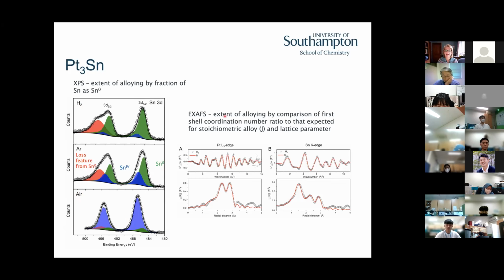Finally, we can do the XAFS and collect the data from the platinum edge and the tin edge. And then we fit that data simultaneously, right? So that the platinum-tin and tin-platinum distances must be the same. So that helps you fit all the parameters that you need, and that gives us another measure of the extent of alloying. And so what is the extent of alloying?